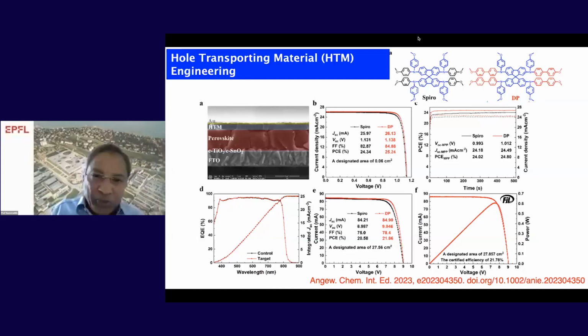So all these dopants enhance the conductivity, but they destabilize the hole transporting material by coordinating the oxidized hole transporting material with the tertiary butyl pyridine. So this is the main drawback of the hole transporting material in NIP configuration. So can we increase the stability of this hole transporting material by increasing the conjugation so that you can move the positive charges in the whole unit?